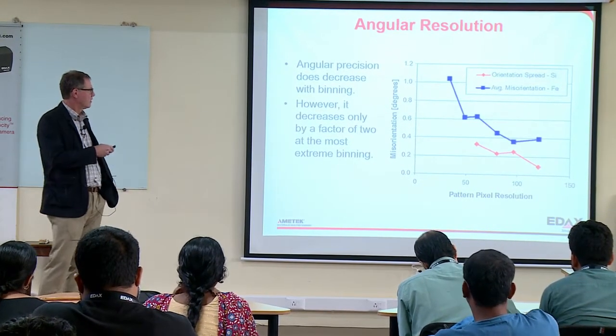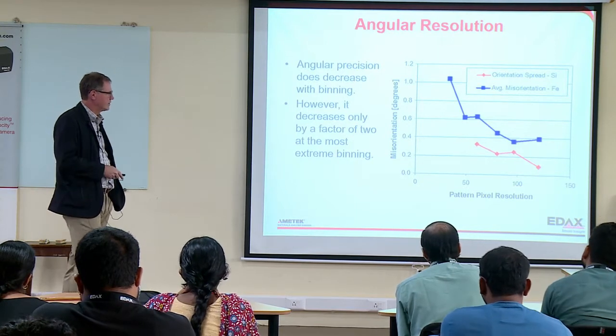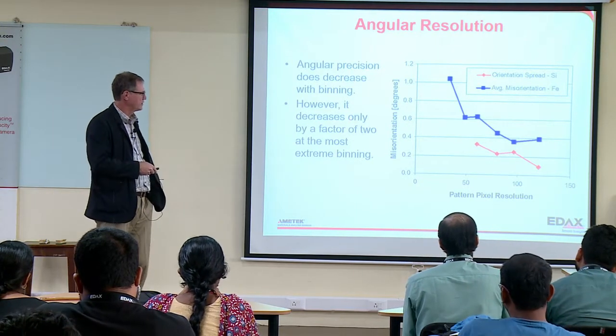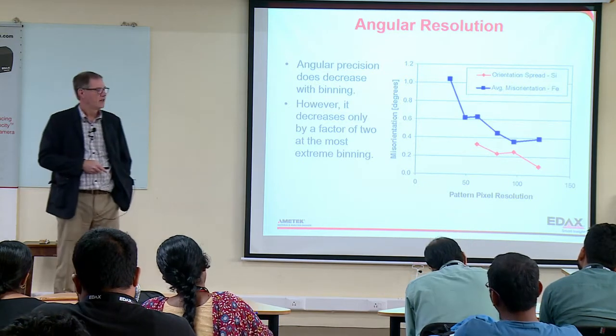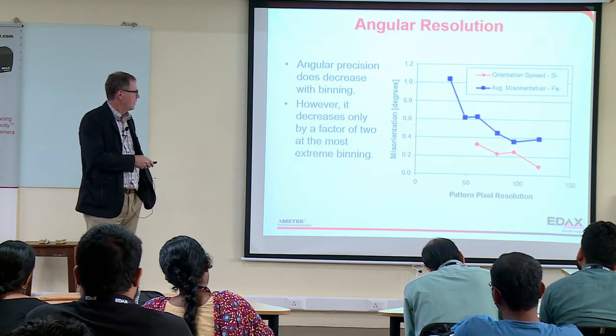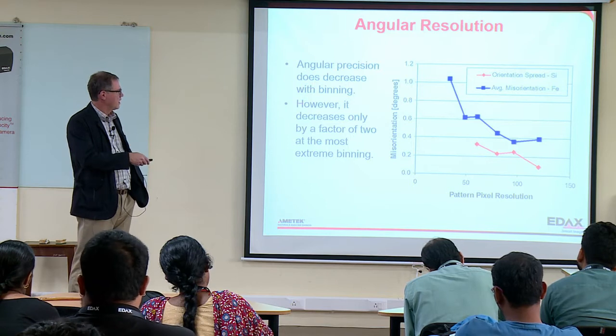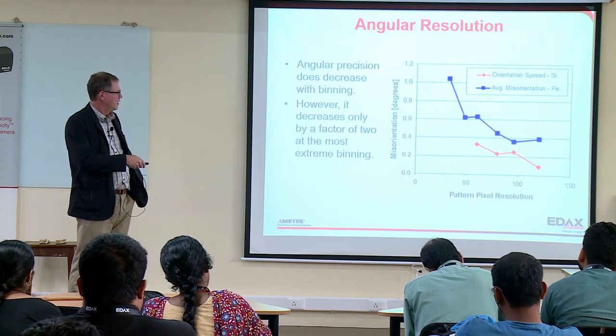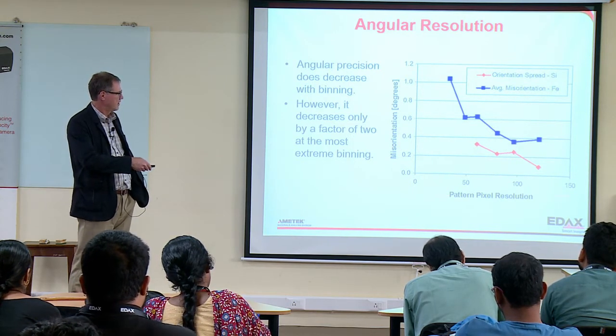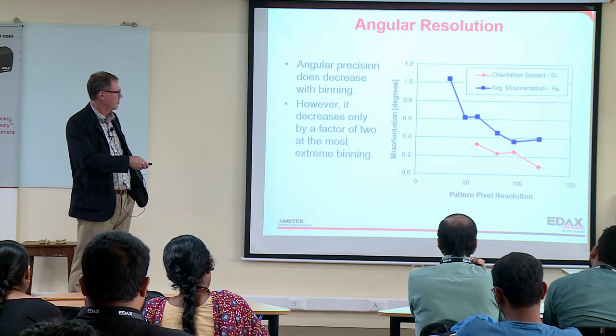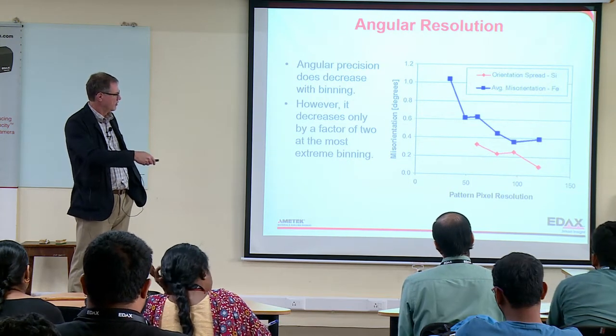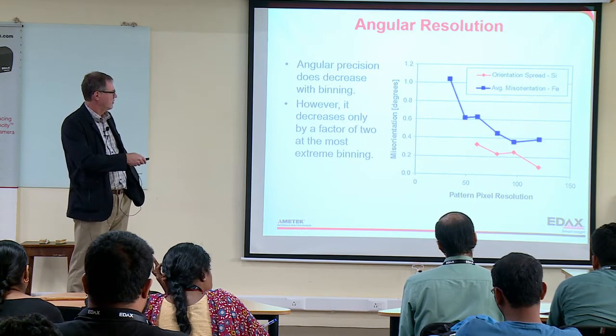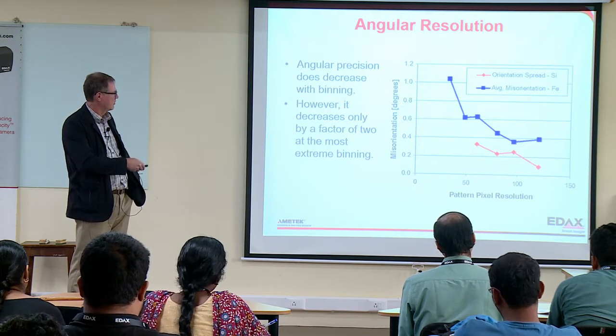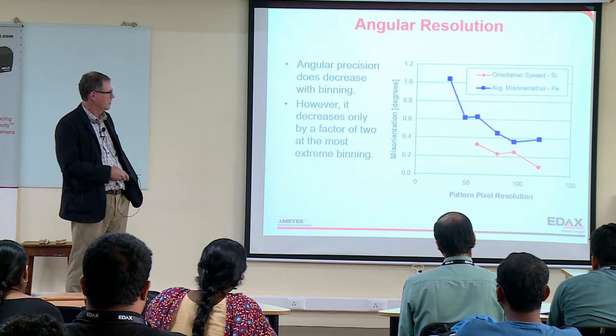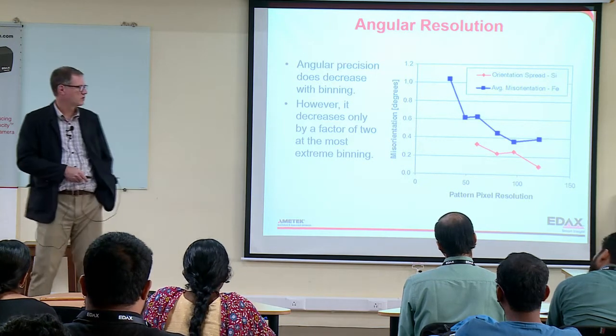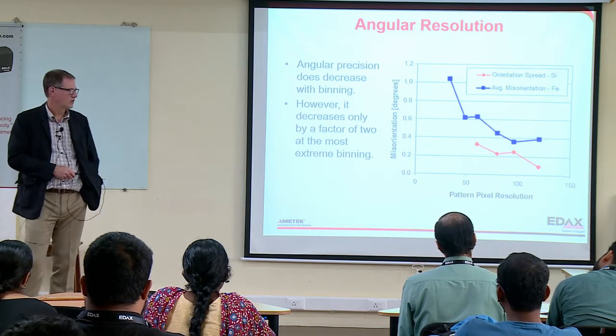Now the angular precision does decrease as we use what we call binning to increase the speed, and I talk about that later. So if we bin it a lot, we can increase the speed. This is higher speed here, lower speed down here. And you can see then the misorientation or the angular resolution drops. So if you really need really good results, don't try to rush it, and you might have to slow down a little bit.